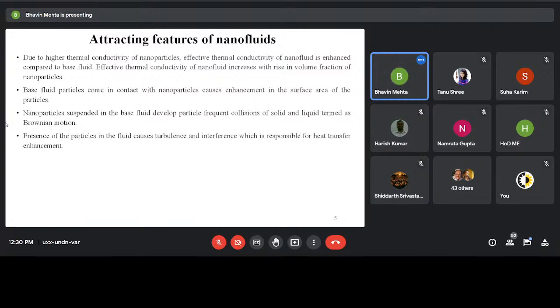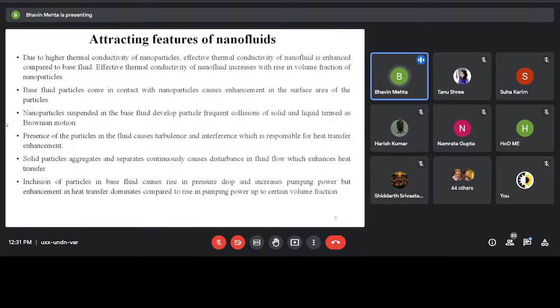The presence of particles in the fluid causes turbulence and interference, which is also responsible for heat transfer enhancement. These solid particles continuously aggregate and separate, and they are also continuously migrating from their places. So that also causes the enhancement in thermal conductivity. The inclusion of these particles in the base fluid causes a rise in pressure drop. That is the adverse effect of the nanofluid.